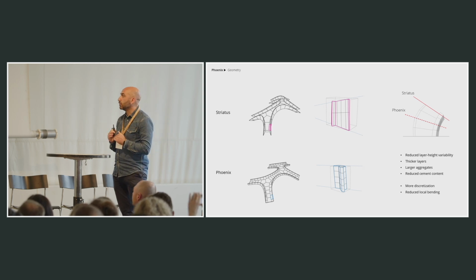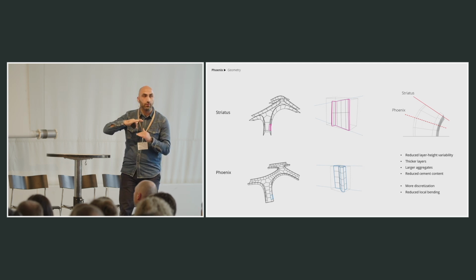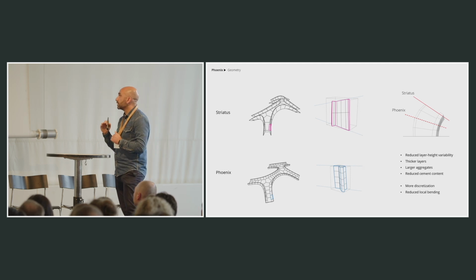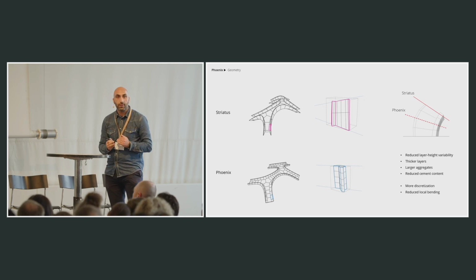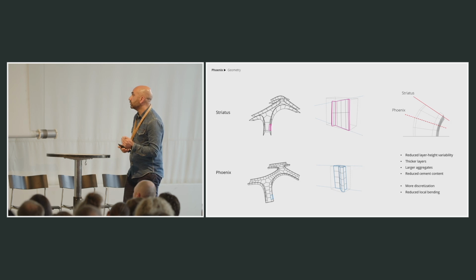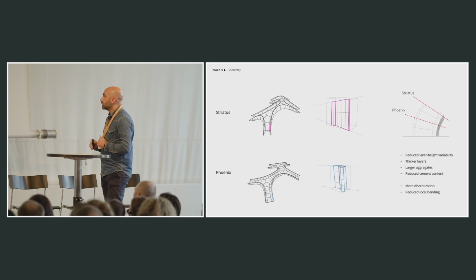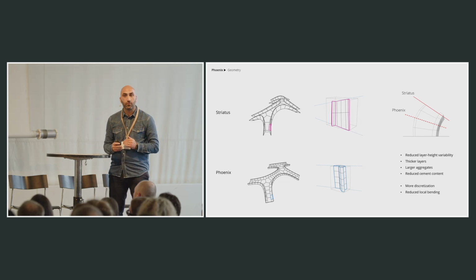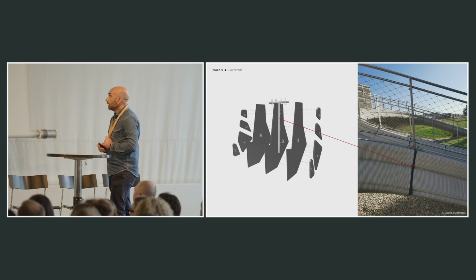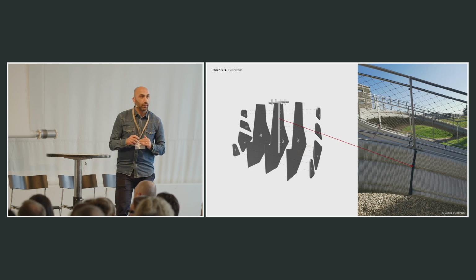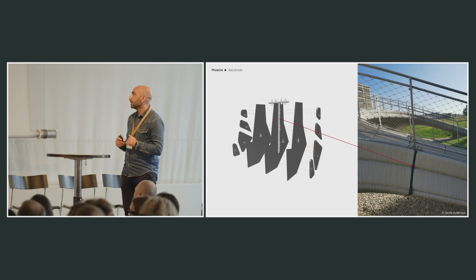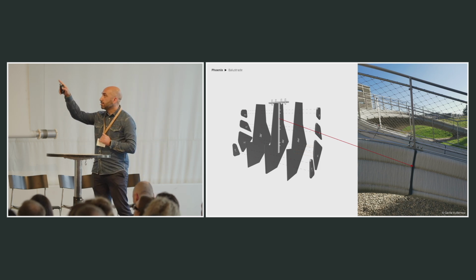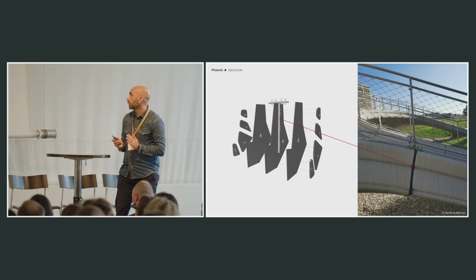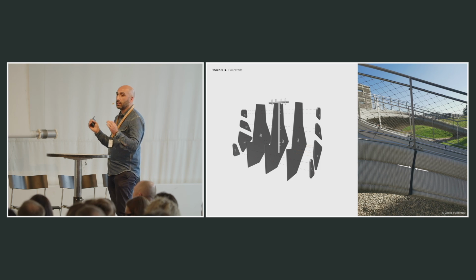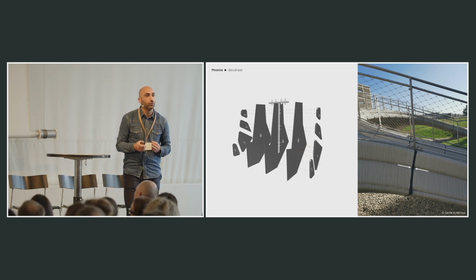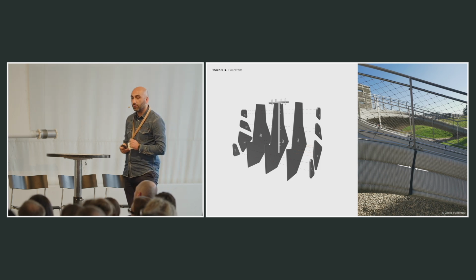So first of all, we reduce the angle between the start and the end plane during printing, which can reduce the layer height variability. We could use thicker layers, which means larger aggregates, and also reduce cement content in the mix. But more discretization also means that we could reduce local bending in the single components from a structural point of view. We also, in this case, integrated a balustrade, like a standard steel balustrade, giving more transparency to the project. And we did that by inserting this steel T element in between the components, which is kept in place simply by the thrust flowing into the balustrade arches on the two sides of the bridge.